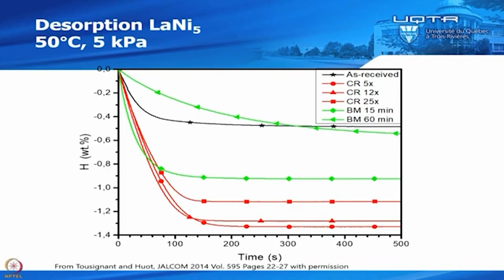So this is the desorption. You see that this is the desorption of the as received, and this is the ball mill 15 minutes. So it's quite fast, and that's the ball mill of 60 minutes. It's slow, but what is interesting is that all of them, the ball mill 15 minutes and all the cold rolling, all of them have more or less the same kinetic. The only difference is the capacity, but they all have the same kinetic. So the point is, after one cycle, they almost have all the same capacity, the same kinetics.